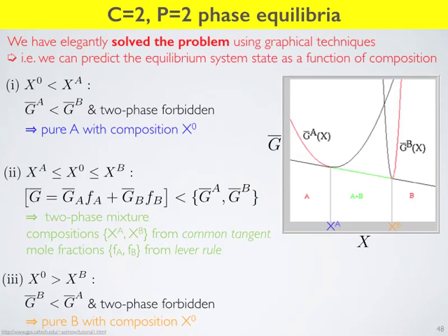One thing that's important to remember is that the common tangent construction defines a tangency condition between these parabolas. So unless these parabolas have their minima at exactly the same point, XA and XB do not occur at the local minimum of the parabolas. It's difficult to see here, so let me try and draw that. If you have two parabolas at exactly the same height, you draw a common tangent, and this common tangent does occur at the local minimum of each parabola. However, if they're at different heights,